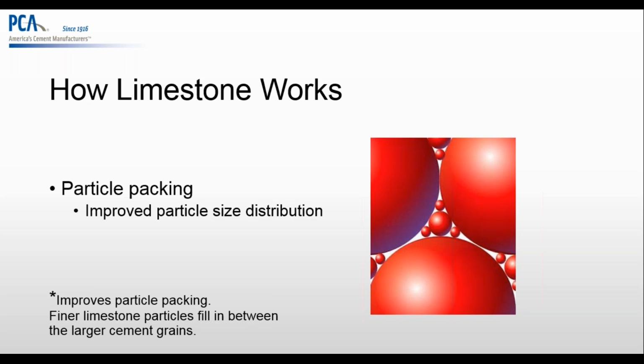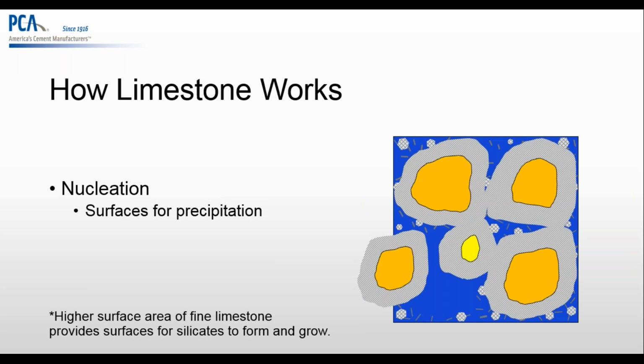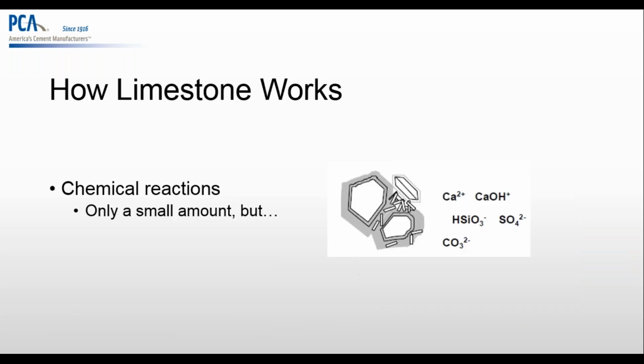So we're counting on particle packing, like Justin said. The clinker and the limestone are interground. The clinker is a tougher material, a harder material. The limestone is softer, so we will have a lot of fine particles. Those fine particles will find their way between the cement particles, and they will fill the voids to have a denser matrix, right? And that's what we call the particle packing, right? So you'll have that. Also, because the particles are closer by, there's nucleation and there's a denser matrix here as well.